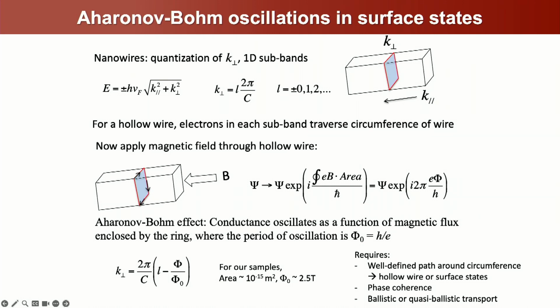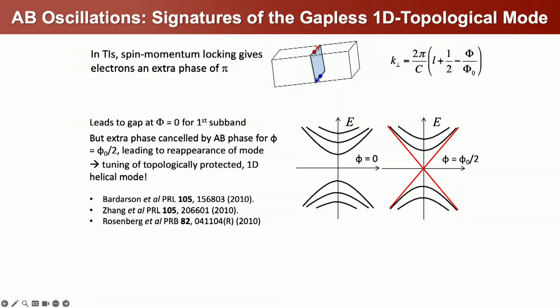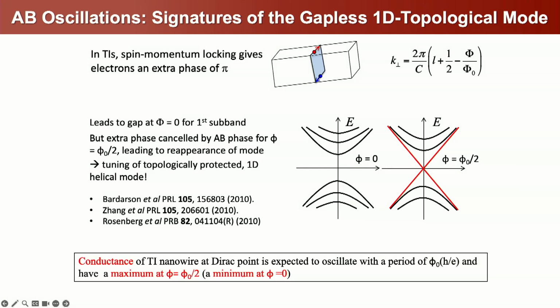Again, without ballistic transport, you'll get other sorts of oscillations that are associated with disorder, as opposed to h over e oscillations. Okay. The other interesting thing about the topological materials is that they have this extra phase of pi, and so what this does is it leads to a gap in the first subband that, if you add a magnetic flux, will cause that first topological subband to reappear. And so in a topological insulator nanowire, you expect the conductance at the Dirac point to oscillate with a period of h over e and have a maximum at half a flux quantum and a minimum at zero, which is unlike what you'd expect in other materials because you have this extra phase of pi.